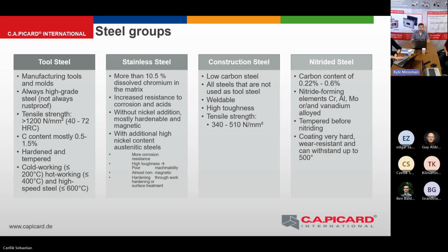And last but not least, we have nitrided steel. These steels are used to be nitrided. That means that they get a coating with nitrogen, or maybe not a coating, but a surface treatment. This coating is extremely hard, wear resistant, and can withstand up to 500 degrees. To do so, you need nitride forming elements like chromium, aluminium, molybdenum, or vanadium. And they normally have a carbon content between 0.2 and 0.6%, so that they are hardenable.